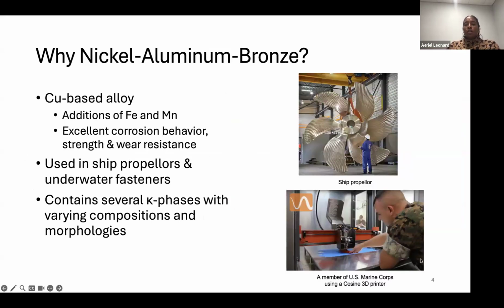So when you think of nickel aluminum bronze, it's this copper-based alloy. It usually has additions of iron and manganese, and those are usually done to change the phases that you get during processing. But it has excellent corrosion behavior, strength, and wear resistance. So if you think about things like ship propellers or underwater fasteners, it's a very good alloy that lasts a long time.